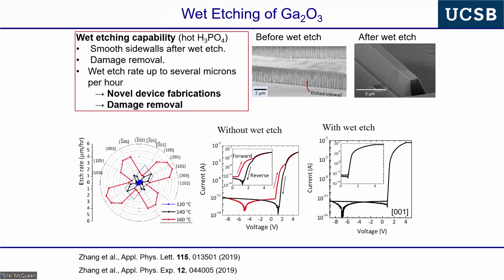So here we can remove material below the ion damage from the etch depth, and then these are the Schottky diodes, sidewall Schottky diodes after wet etch. We recover ideal diode behavior. And this is a huge feature of gallium oxide, that we have a wet etch technology.